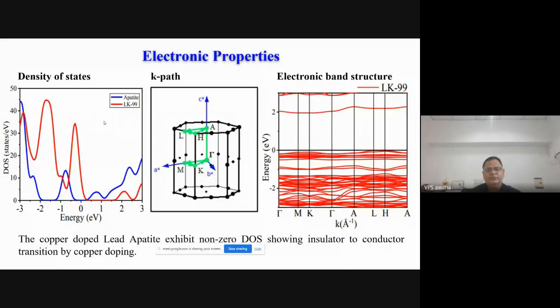One of my students did some DFT and all this type of things also. So what we could see is that copper-doped lead apatite has non-zero density of states, as you can see, the red one and the blue one, which is the apatite without copper doping, it is symmetrical at both sides of zero. So my student could do this immediately, and this was done by many others, whose papers were coming on the arXiv. That shows that lead apatite, which is an insulator, if doped with copper selectively, can show conductivity and in fact can lead to superconductivity as well.